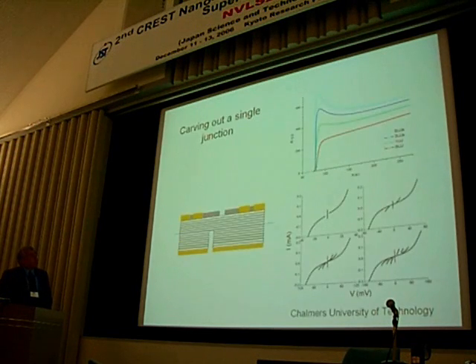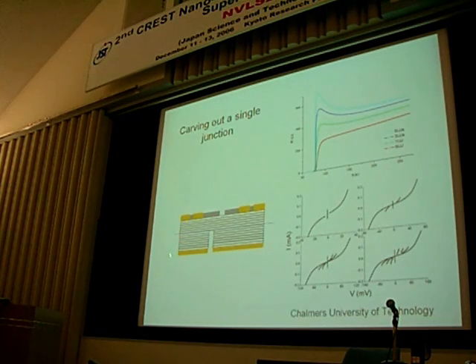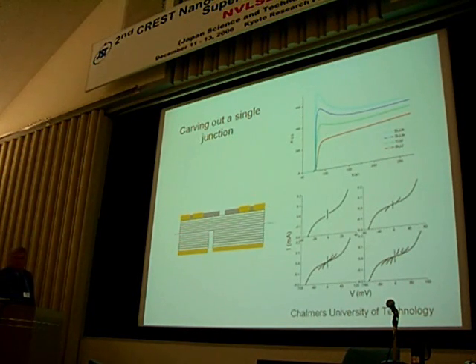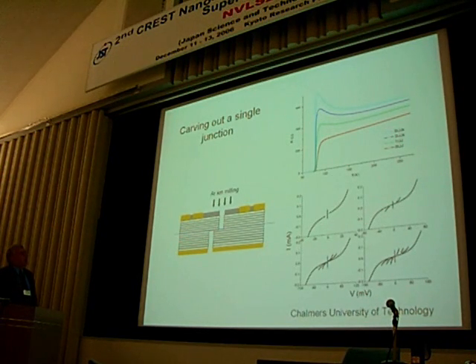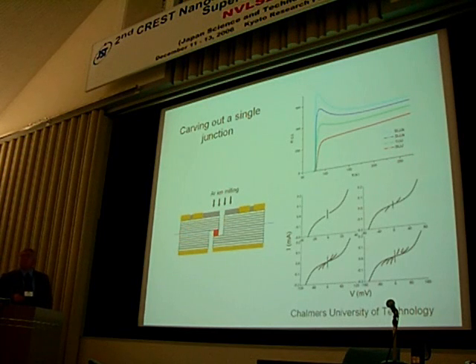The other two types I would like to mention are the intrinsic junction, the bismuth compound, and also the thallium compound. You have these very nice long planes, and you can try to cut out these planes just with focused ion beam milling. And you'll get then, if you're lucky, one coupling or more, and this gives you junctions as well.